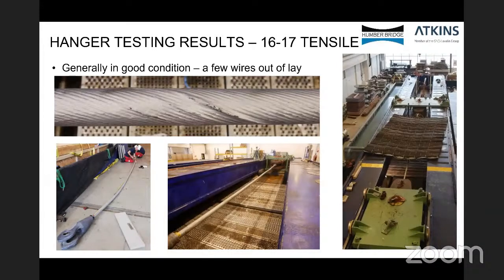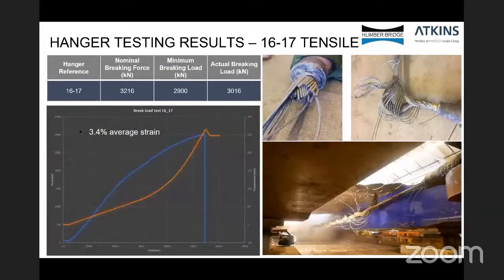If we go on to the next slide, we can see some of the test results. So for this first hanger, it achieved an actual breaking load of 3,016. This was less than the original 3,216 nominal breaking load, but greater than 2,900, the minimum breaking load specified. So essentially it passed the test.